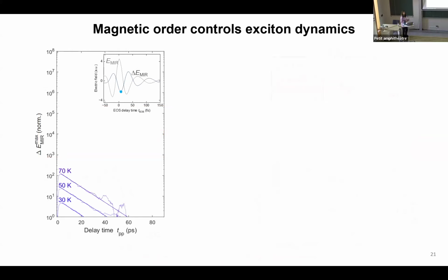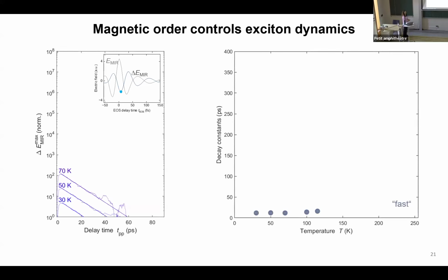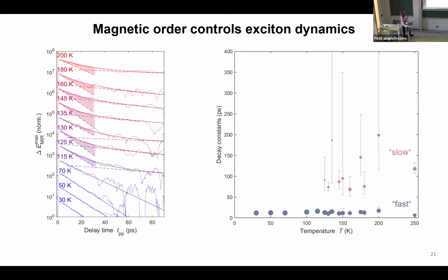What we see is that below the Néel temperature, we have a relatively fast recombination to the ground state. It is occurring at a time scale of about 10 picoseconds. It is a single exponential decay, nothing very interesting actually. However, when we go above the Néel temperature, on top of the fast initial decay, here comes another slow decay constant, which can be as high as hundreds of picoseconds. And this double exponential behavior is giving us some information that there might be two excitonic species involved in the ultrafast dynamics.